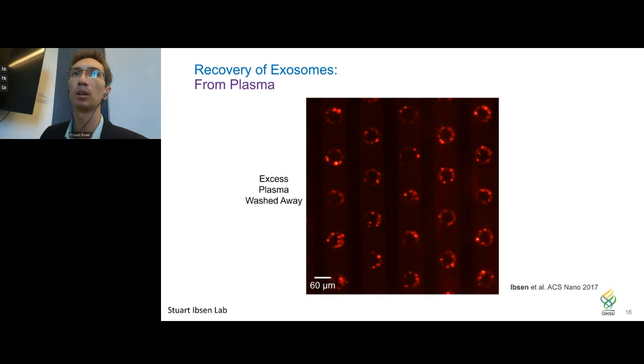Now we get two added benefits from this as well. The first is that we get a concentration of the particles around the electrode edge, so we get a better signal to noise ratio. And then the second thing that's really good about this is that we know where they're located. So we can come in with our various stains looking for biomarkers, and we'll know where to look on the surface of the electrodes because we know exactly where the particles are located.